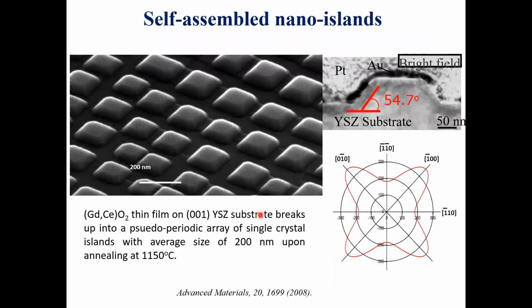So if we take a closer look at the nano-islands, we see a remarkable size similarity, and also some sort of alignment. You can see that they're ordering in some self-assembly type scenario, where we find that these nano-islands are aligning along the softest elastic modulus direction of the substrate.